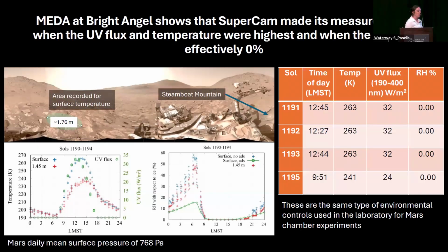A lot of these Mars chamber experiments do happen at room temperature, which might motivate the fact that we see some of these changes happening to these hydrous minerals. But MEDA also tells us that the relative humidity is effectively 0% at the time that these measurements are happening.